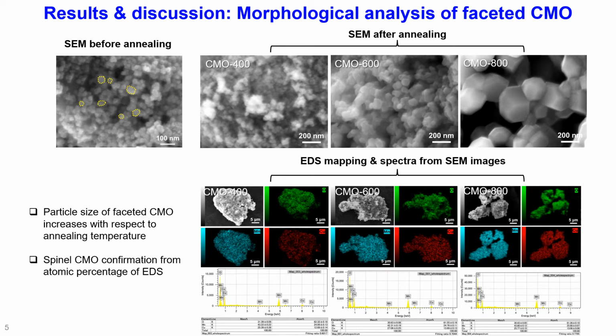And then EDS mapping and EDS spectra from the SEM images. Here we can see the uniform distribution of elements like copper, manganese and oxygen in CMO 400, 600 and 800 respectively. Here we could also confirm the atomic percentage of copper, manganese and oxygen as 1:2:4, which further confirms the spinel formation of CMO.